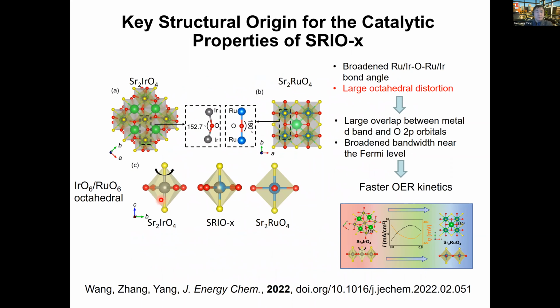And if we look into the composition tuning, what we think the major structural feature is that we change the order to a disorder by using either iridium or ruthenium, because they have different bond angles in the corresponding pure phase. You created a maximum size distortion in this particular case, and that happened to lead to the maximum performance. So the specific reason linked to this still needs to be determined, i.e. whether the d-band, this was a hypothesis, i.e. whether the broadening of the band near the Fermi level, as previously, could contribute to this. This may need some simulation based on quantum mechanics in the future. So that's beyond us.